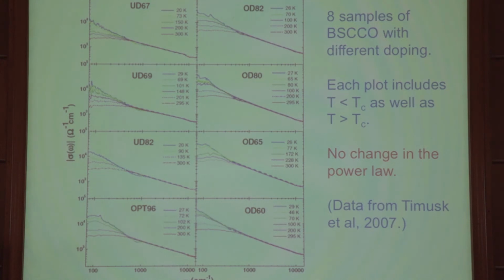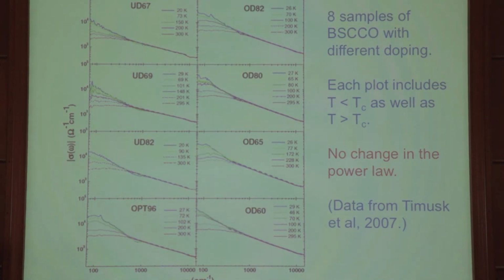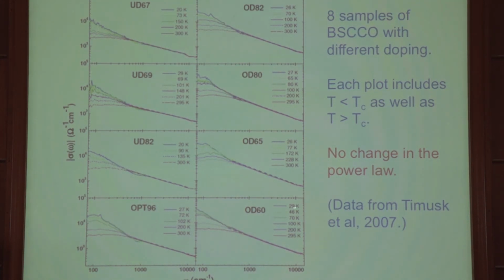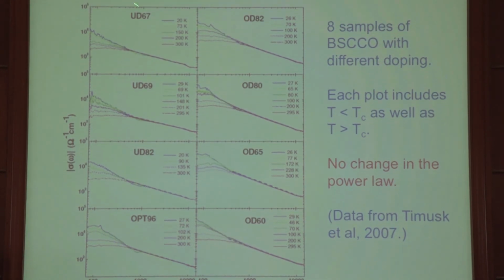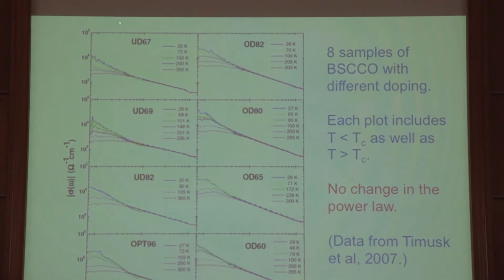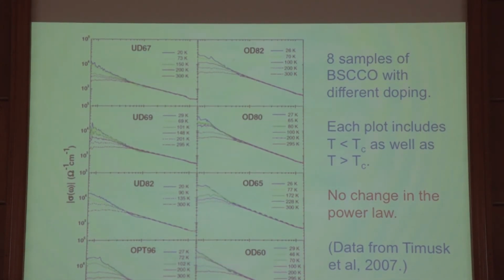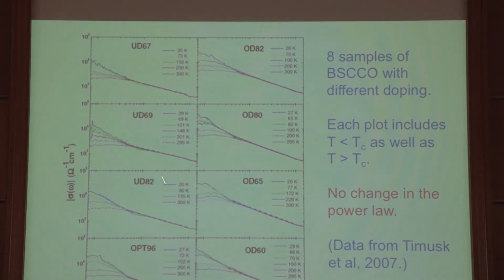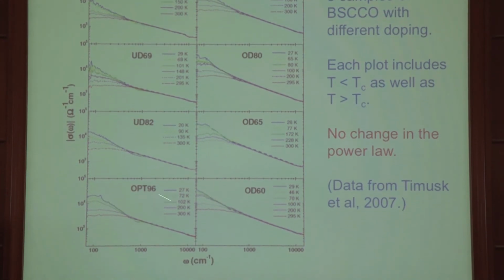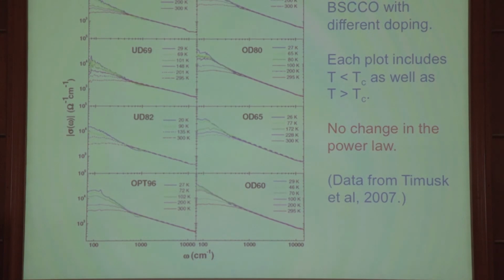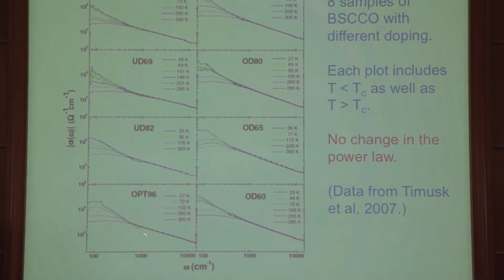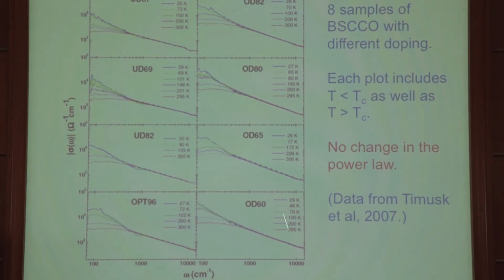This is now eight plots showing eight different samples of this material BSCCO, which differ in something called the doping. They replace a certain fraction of the atoms with some other atom to increase the number of free electrons. In each plot, there's the absolute value of the conductivity as a function of frequency. These are log-log plots. Let's just look at one of them, because they all look very similar. I should say what the label is giving you. UD is underdoped, and the next two numbers are the critical temperature. So this material goes superconducting at 67 degrees Kelvin, then you increase the doping, and the critical temperature goes up to 96, that's optimally doped, and then these are overdoped, and the critical temperature goes down again, all the way down to 60.